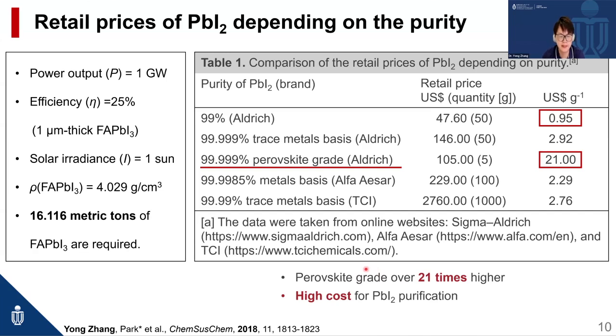So we thought we could directly purify the lead iodide by converting it to the perovskite. During this synthesis process, we can purify this lead iodide by removing some impurities.